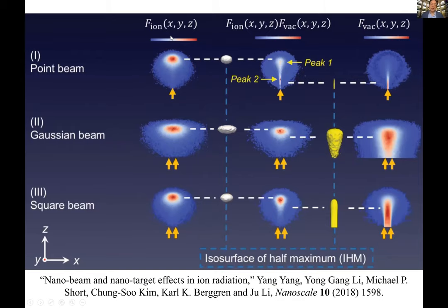We can also design, for example, one ion beam, which could be a nitrogen beam, with another beam which creates vacancies to create nitrogen vacancy centers. These are used for quantum computing in diamond. So we can model when you have one broad beam and maybe one nano beam, what kind of certainty you can have in creating these nitrogen vacancy centers.